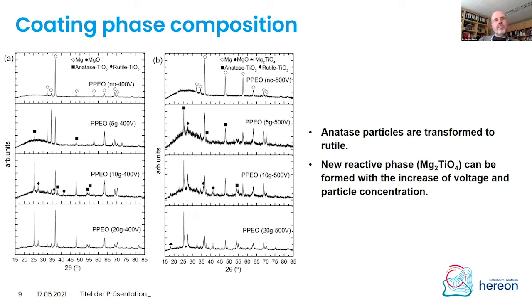And if you compare 400 and 500 volts, you see also that at the higher energy you are stimulating reactive incorporation, which we normally do not really want to have, because it will destroy the photocatalytic activity of the particles which we added when we are forming the magnesium titanate phase. But it has another effect when this phase is forming, because then you get nice colorful blue coatings. But this is just a side effect which was not of interest for us in this application.